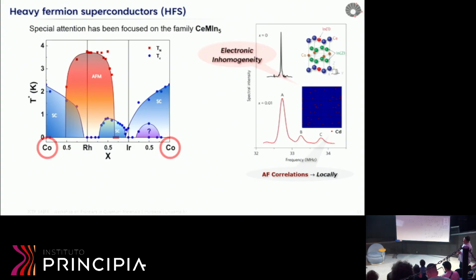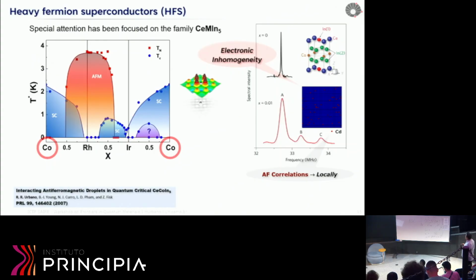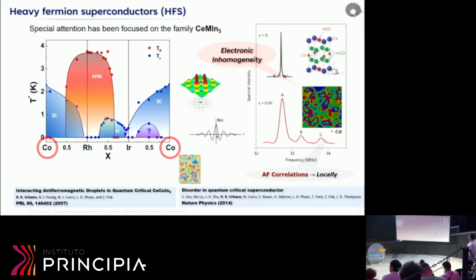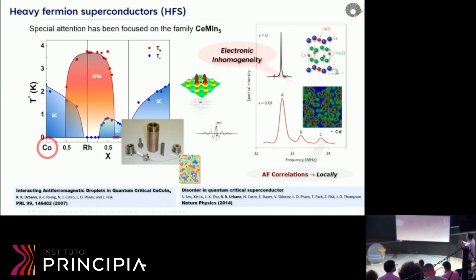And the way we explained it was through a very electronically inhomogeneous scenario, where when you dope this system, you introduce an impurity, a magnetic impurity, with some correlation function. So when you cool down the system, this correlation grows and eventually overlaps locally, and then you reach T_N with that. In a different work, we also showed that by applying pressure, we kind of suppress these correlations. However, the system, although going back in this direction in the phase diagram, never recovers the quantum criticality. So the scenario is really complicated there, and some caution must be taken into account.